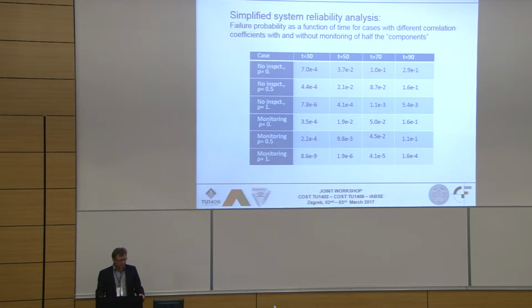That means if your correlation is 1.0, it doesn't matter if you have 90 components or 1, because all information is contained in each single component because they are fully correlated. So it's really not a system with 90 components, it becomes a system with 1 component. So then you have a large effect of having information about reduced surface concentration. So we go down to 8.6 times 10 to the minus 9 for the 30 years, and also for the other durations up to 90 years, we have a very strong effect of doing monitoring. But 0.5 is not that strong a correlation. Observations are that you need a correlation of 0.8 or higher before the correlation effect comes into play on the system reliability values.